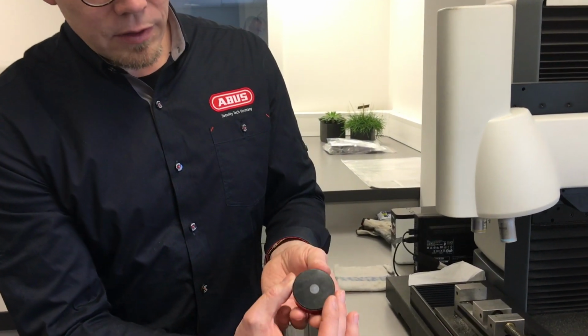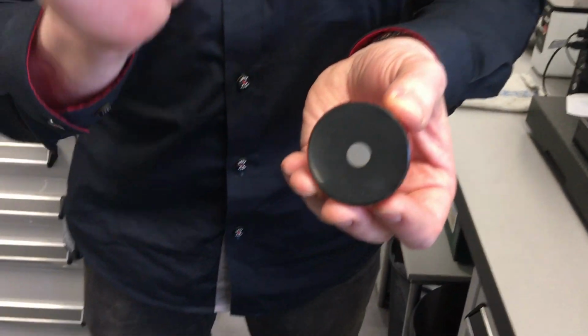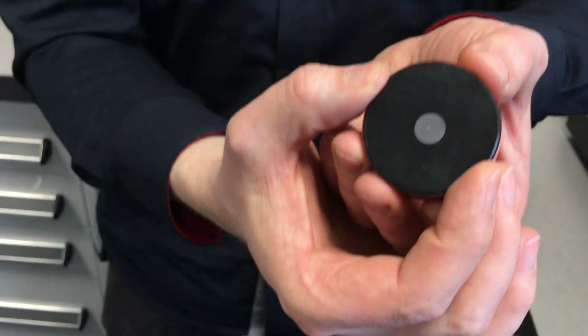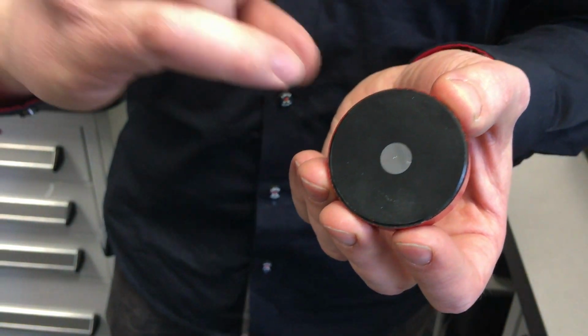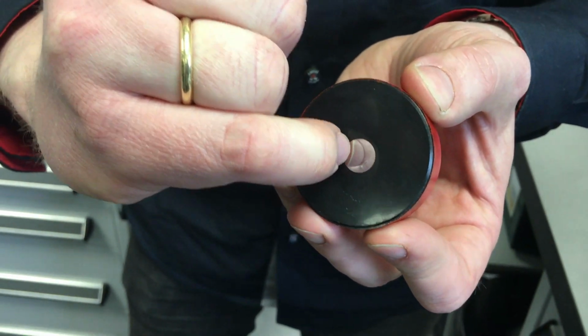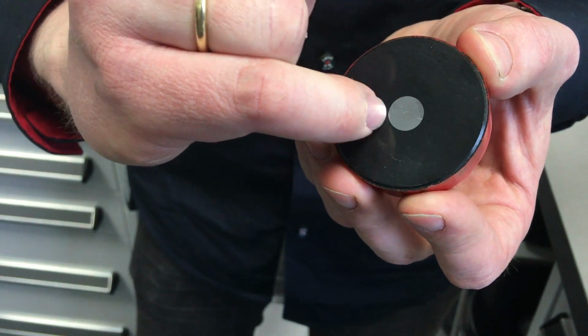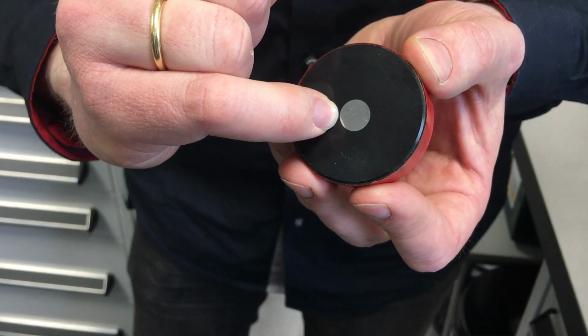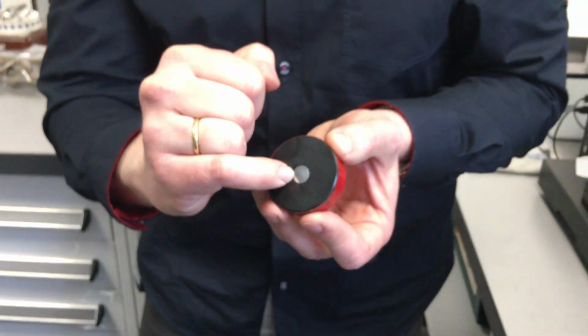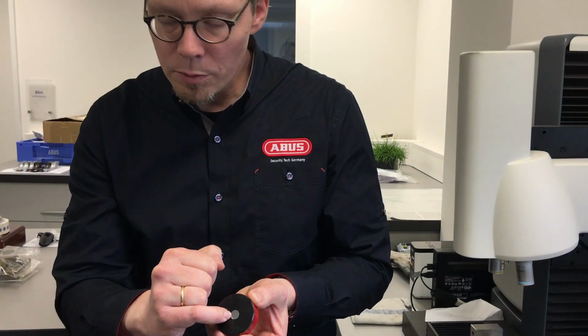Here, we have a piece of the shackle. We cut out that piece and place it into plastic. We polish everything, and now we can check with a diamond pyramid in the middle of the shackle, closer to the edge, and even here at the edge. Then we measure 0.1 millimeter away from the edge, and then 0.2, 0.3, and so on. And then we can see how hard the outer surface is and how hard it is inside. So we can say 0.2 millimeter, 0.3 maximum, that's what we allow. And this is how we test the hardness of the steel.